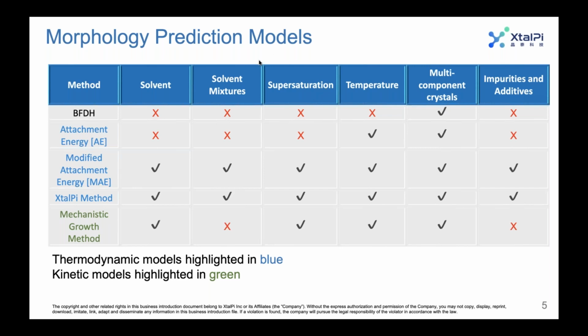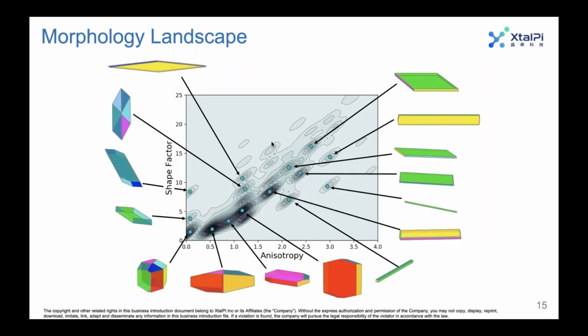Okay, that sounds good. The next question is, what if the morphology calculations end up predicting only needle habits? Yeah, so that's possible. Let me go to a morphology landscape. Okay. So for every system that we've studied, the morphology landscape is unique, but it does usually encompass some combination of prisms, plates, and needles. So I guess the question here would be, what if we did 15 simulations and all of those simulations predicted needle-like structures? That would be a little bit unfortunate because it would suggest that the experimental variables like solvent or supersaturation are not enough to change the morphology.